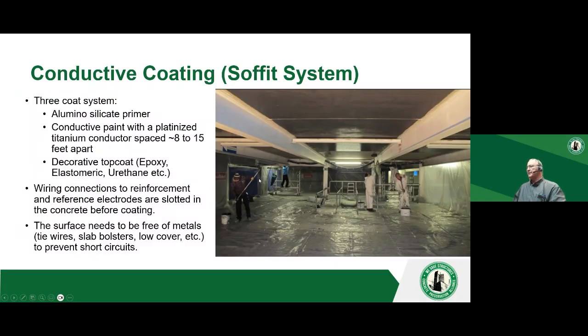Then we do conductive coatings. It's very similar. It's a soffit system. The key for the conductive coating systems is that you have to isolate it from metals so that you don't create short circuits. It's an impressed current system. It's typically a 3-coat system. You're going to do all your surface prep, put a primer on, put the conductive paint, and then put a decorative top coat.